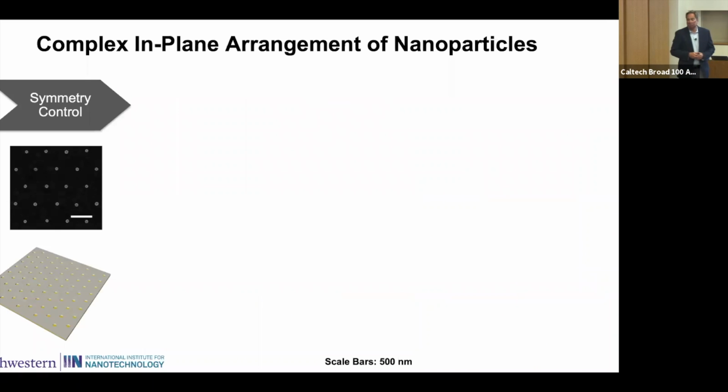Okay, the other neat thing about this is I can control where bonding sites are. I showed you that in proteins. I can also do that in surfaces. So our version of epitaxy is putting oligonucleotide bonding elements on a surface and then growing structures from the bottom up. But you can do this in a really sophisticated way. For example, you can begin to create holes in resist that at the base of the holes, you modify with oligonucleotides that recognize particles.